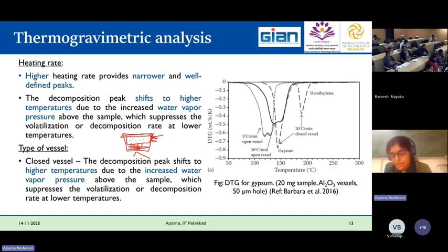So here what is happening is you have a gypsum. Gypsum is calcium sulfate 2H2O. Now gypsum is dehydrating to hemihydrate. Hemihydrate is 0.5 H2O, means 1.5 moles of water has been lost in this weight loss that we are seeing. And now we have another system with 0.5 H2O. That 0.5 H2O has been lost at even higher temperatures. So now gypsum, upon dehydrating, has converted to hemihydrate, and now hemihydrate has dehydrated totally. That is what this gray dotted line tells us.